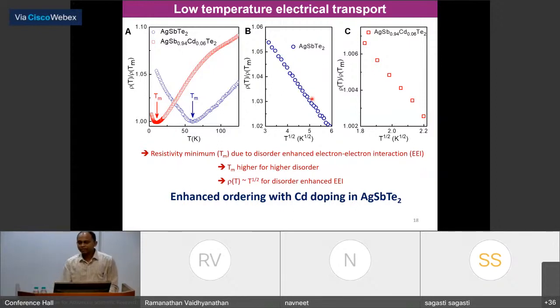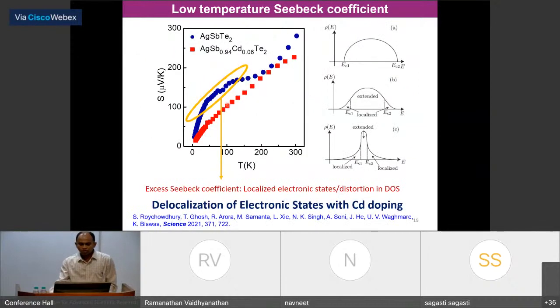Now you remember the famous Mott equation I showed, that in the Seebeck coefficient we should see an increase if there is a localization because of deviation from the parabolic band structure. So this is the low temperature Seebeck coefficient of a pristine sample which has a disordered cation of silver and antimony. But as soon as we dope cadmium, we see a decrease in the Seebeck coefficient, the broad hump goes away. So that means as soon as I dope cadmium, silver and antimony is getting ordered in the system and the electronic states are getting delocalized. So that's what we wanted. So there is a direct proof from the low temperature transport data, electrical resistivity and Seebeck, that delocalization of the electronic states is happening with cadmium doping.